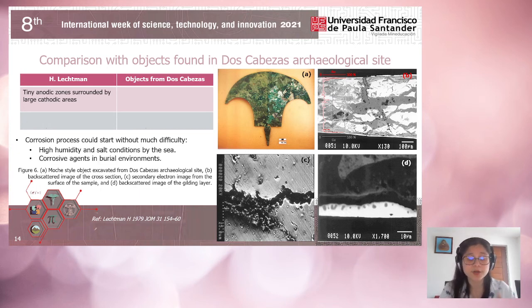Even more, in the burial sites where these archaeological objects were found, there were a lot of corrosive agents such as chlorine, which means that perhaps we could have seen more copper corrosion in these conditions. As you can see in figure 6, which shows the objects found in Dos Cabezas, especially in figure 6c, you can see the solid diffusion of copper oxide through the gold film, scratching the plating and erupting from it. And you can also see from figure 6a that this corrosion expands throughout the whole piece.